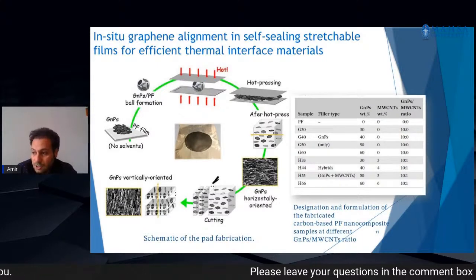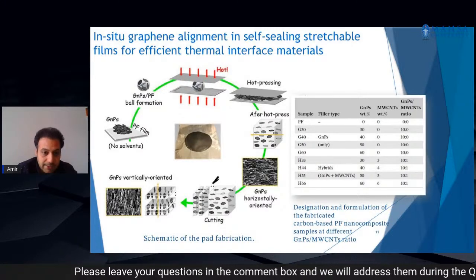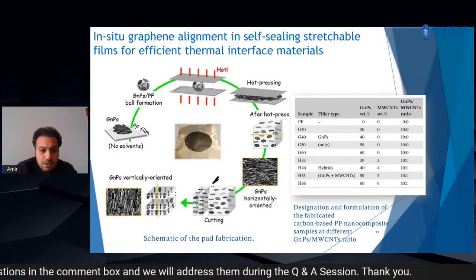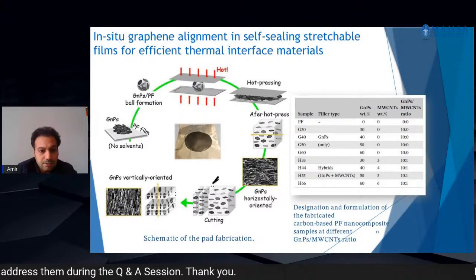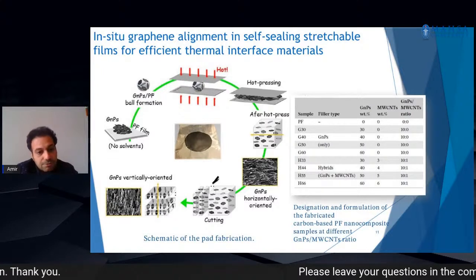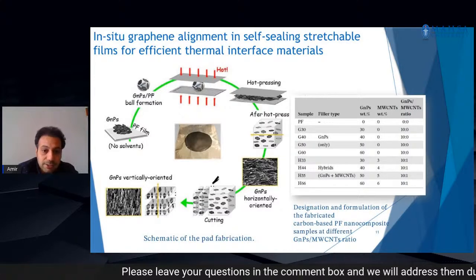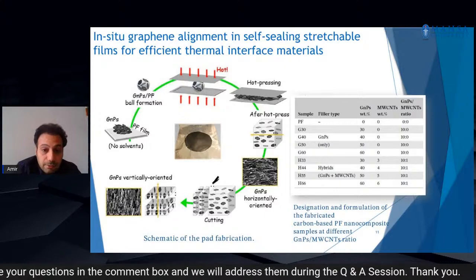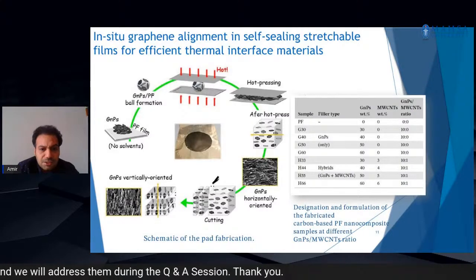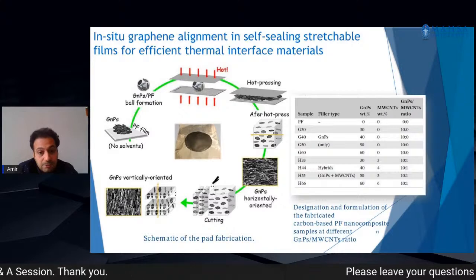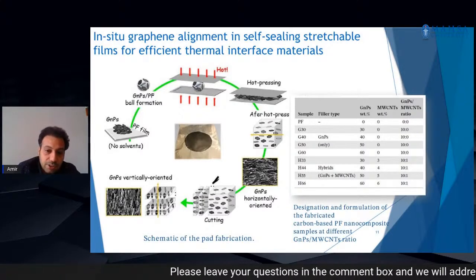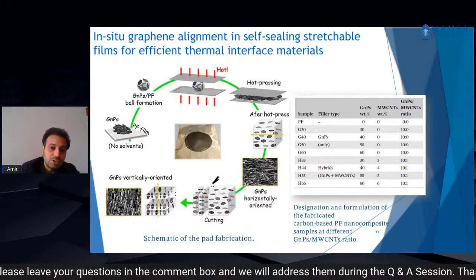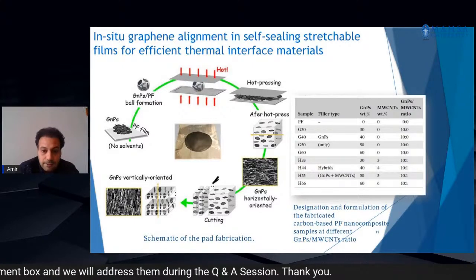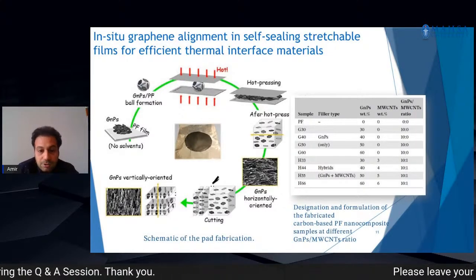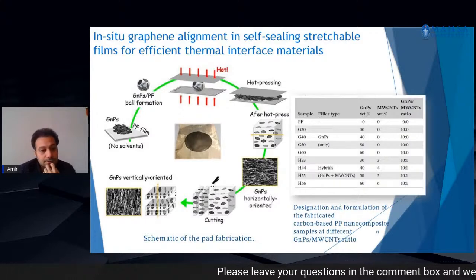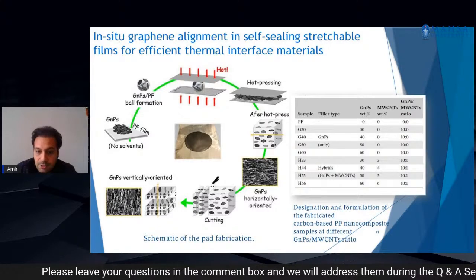Hybrid pads were also constructed with MWCNTs, multi-walled nanotubes. So the process that you can see is we combine GNPs with the paraffin, and then make a ball formation, and we press it. We press with a hot press at a temperature around 60, and try to make the film. After the hot pressing, we have one horizontally oriented GNP film. Also, we cut and make it vertically oriented. So here are the samples that we worked on, and we compare only GNPs, and also what we call hybrid, a mix of the GNPs with multi-wall MWCNTs.